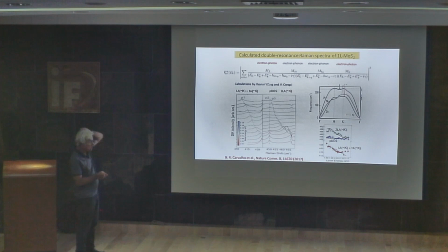And this was a theory that was done by the group of Vincent Crespi at Penn State and Yuan-Shi Wang. They calculated this so-called intervalley process, and they could show that some peaks are dispersive, explaining our results. And finally, the last thing that I will show you is the Raman spectrum of 1 layer, 2 layers, 3 layers, and 4 layers.